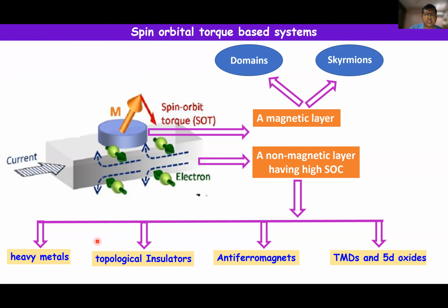In that respect, topological insulators come to the rescue. They exhibit very interesting properties, and they have these spin momentum locked surface states, which can exhibit high spin orbit coupling. Or antiferromagnets, because we have a lot of antiferromagnets, and most of them can exhibit high spin orbit coupling. The antiferromagnets have other advantages too, but for the spin to charge conversion, you can use them as a good material. And of course, there are other possibilities like transition metal dichalcogenides like MoS2, MoSe2, and so on, or 5d oxides like iridium oxide, ruthenium oxide, and so on.